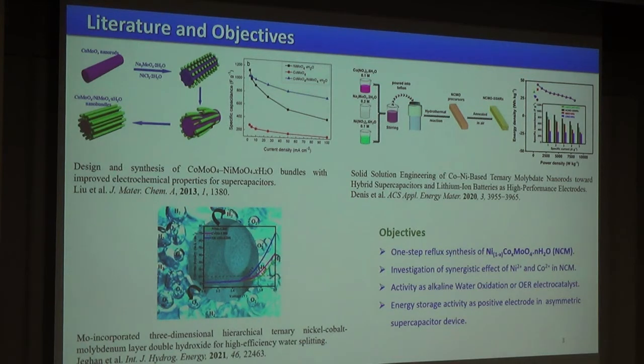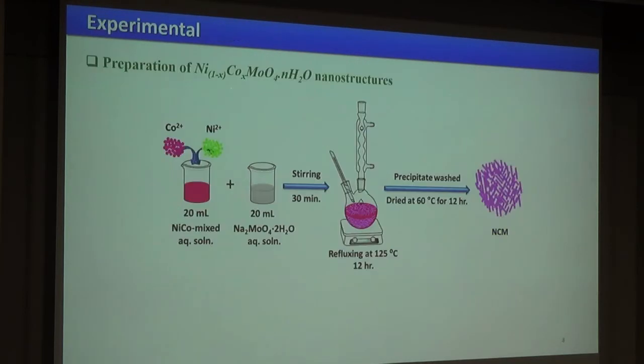So our focus or motivation is to prepare this material in a one-step process which can be scalable, and also to study both its energy conversion and energy storage activity. So this is the experimental procedure or synthesis procedure of this material, where a one-step reflux method was utilized, mixing the equimolar aqueous solution of cobalt and nickel with aqueous solution of sodium molybdate hydrate.